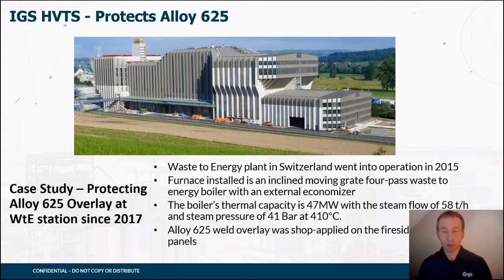So from the conceptual design, this boiler was intended to be a very low maintenance unit. They didn't want to have extended shutdowns. They were trying to achieve extremely high uptimes, above 97%. In order to do that, they eliminated all refractory in the boiler, because the operators considered the refractory often the weak point in the unit when it came to repairs and outages. And it was always the refractory repairs that took the time and extended the shutdowns when they had to have the boiler out of service.